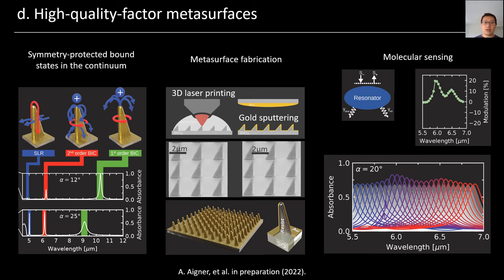So for the structures we considered, first we use the 3D laser printing to put these 3D triangular structures in the polymer, and then we do the gold sputtering and coating and make it a plasmonic metasurface. And then we can put these molecules on top of the metasurface, before and after. We can make this metasurface sensing area very large, and each small pixel has a different resonance. And then if you attach this with the molecules, the molecular response can also be observed, which is a very cool application of this metasurface for sensing devices.